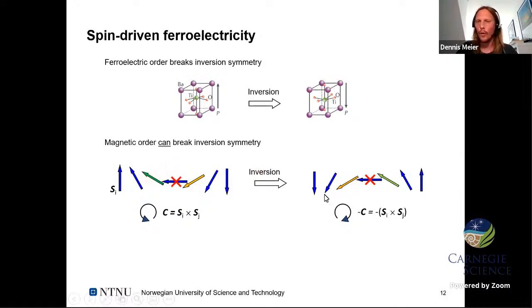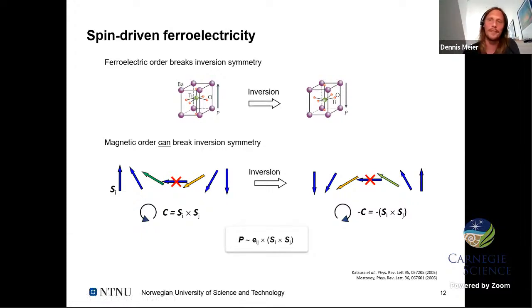And when I do that for all spins within the spin system and look again at the chirality, you see it's now opposite. The spins are now rotating clockwise. So inversion symmetry is broken. After applying it, I go from a counterclockwise to a clockwise structure of the spin system. And that can then give me a spontaneous polarization as expressed by this formula, which was first written down by Mostovoy in 2006, and it became really one of the most important formulas in spin-driven multiferroicity.